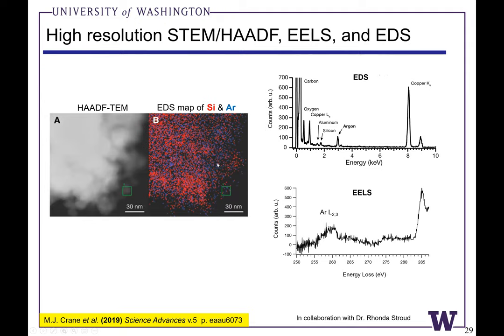And we were shocked that in this process, not only have we loaded silicon atoms into the diamond material, but also somehow we had formed argon point defects in the sample. And we could see, Rhonda could see these argon atoms also from energy dispersive X-ray measurements with EDAX in her microscope. We could see this at the University of Washington as well in our less spatially resolved microscope. Rhonda also was able to see argon from the L2, L3 edge using electron energy loss spectroscopy. So we knew argon atoms had made it into the diamonds, but we were really surprised by this.